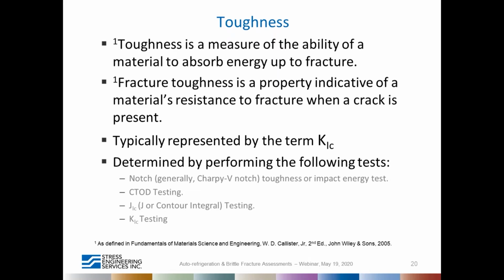The cheaper test is the notch toughness. The typical one is the Charpy V-notch. It is not a direct measure of toughness, although there are correlations that exist that give a clear indication of where the toughness is. There is CTOD testing, also known as crack tip opening displacement testing, and then J1C testing and K1C testing.